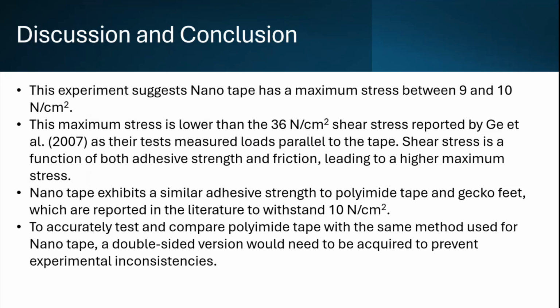I found that nanotape exhibits a similar adhesive strength to polyimide tape and gecko feet, which are reported in the literature to withstand 10 newton per centimeter squared. And then to accurately test the polyimide tape, I need to get a double-sided version of the tape to use the same method as I used to test nanotape.